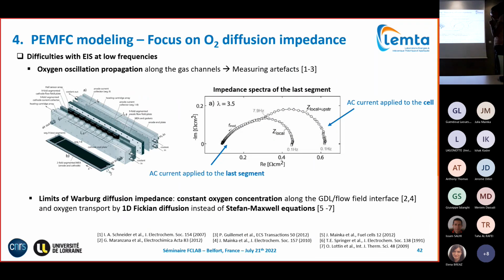Low frequency interpretation is a little bit tricky because you have, on the one hand, some artifacts coming from the measurement signal, which are very important when you analyze local spectra. What's shown here is from colleagues at the PSI in Zurich, who compared a spectrum measured when applying the perturbation to the overall cell, and a spectrum measured by applying the current perturbation only to the last segment.